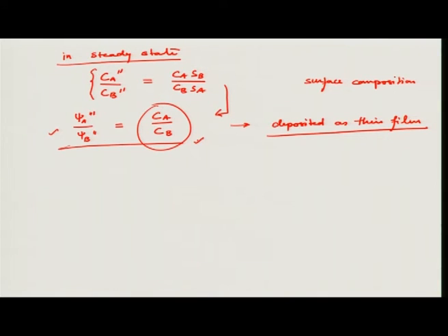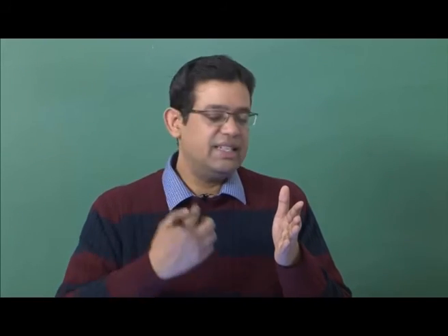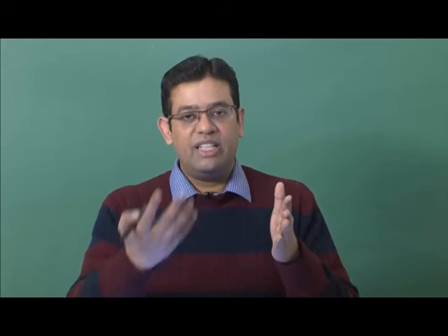The only condition is that you should allow time for pre-sputtering. Pre-sputtering has two reasons. First, you can remove anything that is deposited on the surface or adsorbed, any gases, any unwanted species.